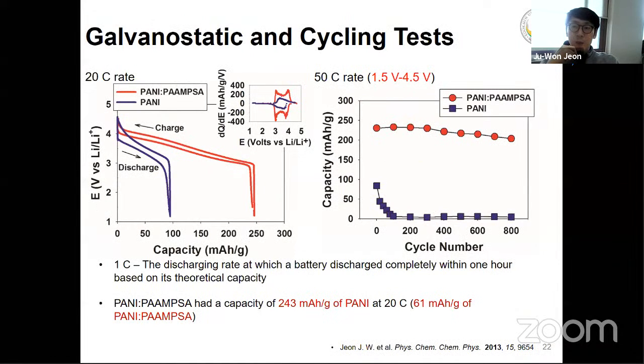So we measure the capacity based on the mass of the polyaniline alone. Polyaniline has a capacity around 100, but PAAMPSA has a capacity around 243 milliampere hour per gram of the polyaniline. But if we convert this capacity based on the PAAMPSA polyelectrolyte, this capacity is 61, which is smaller than the polyaniline homopolymer electrode. And maybe this is the most important data in the first part.